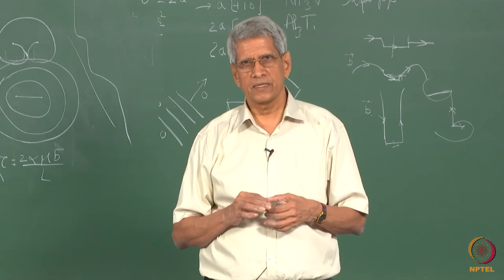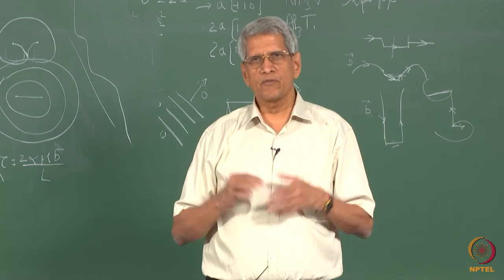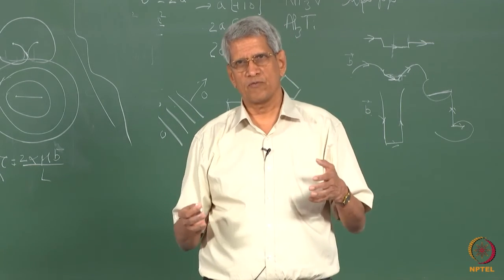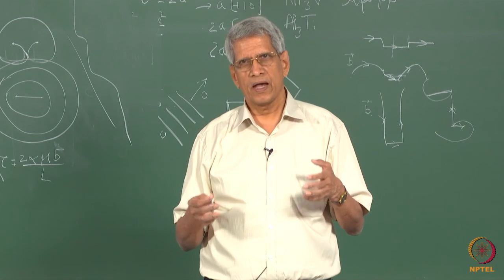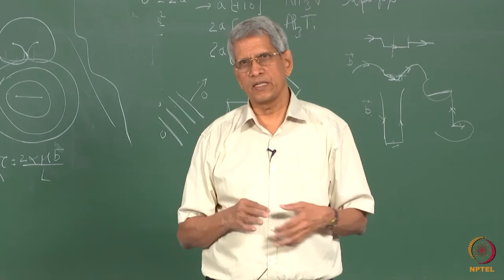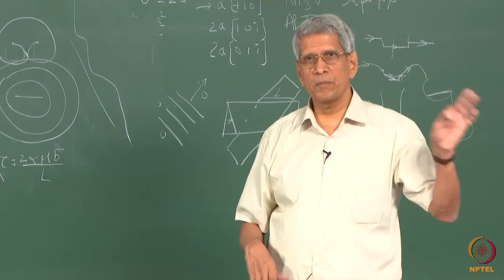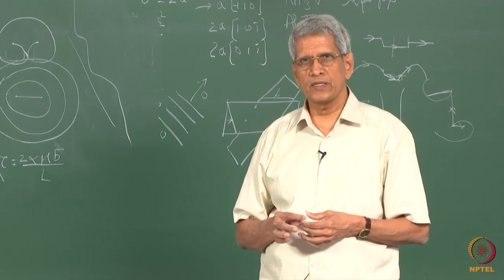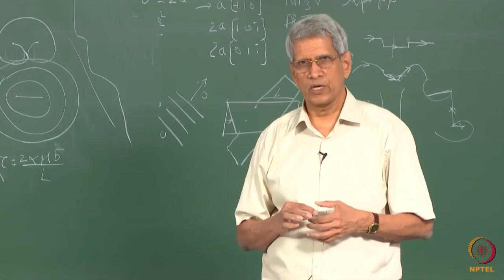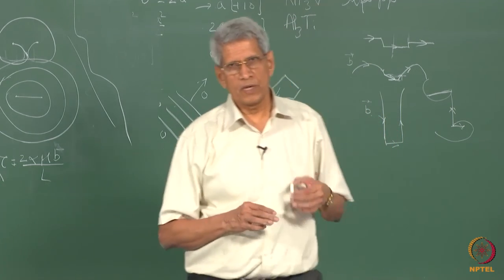In such cases, a lot of stress concentration can build up. Like in the case of aluminum, where the stacking fault energy is high, cross slip of dislocations can take place to relieve that stress. Here, if this is an edge one, none of them can cross slip either. That is how a build-up of stress will occur in the sample. So, we will stop here.